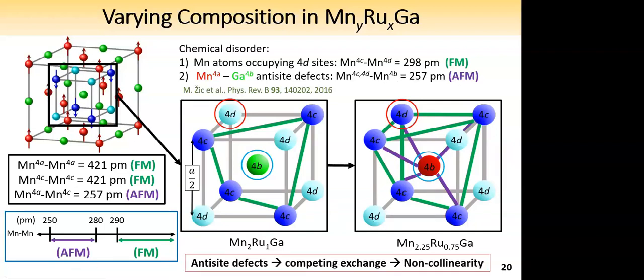What does that mean? Well, anti-site defects could lead to competing exchange, which could lead to a non-collinearity of the sublattice moments. And this is an important consequence. This non-collinearity, if it's strong enough, would manifest itself as canting of the net moment at zero field. So now I'm going to present the SQUID and the anomalous Hall effect data, and we're going to see if we see any signs of non-collinearity.